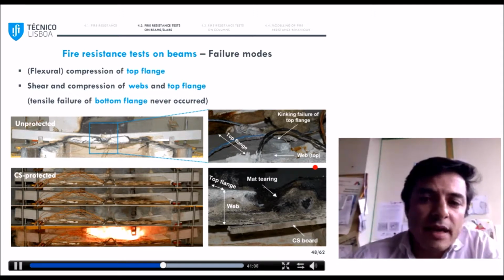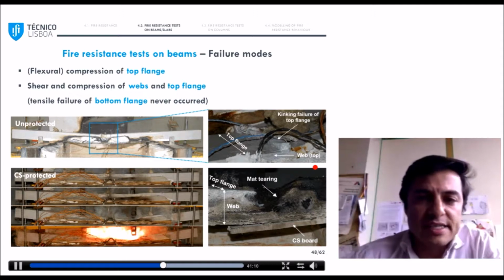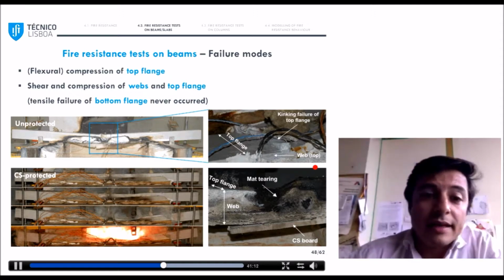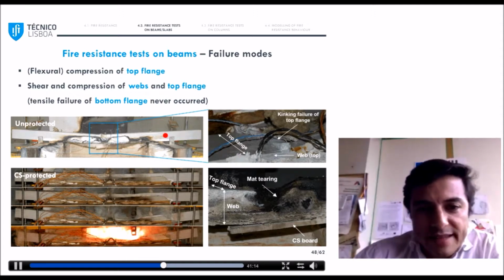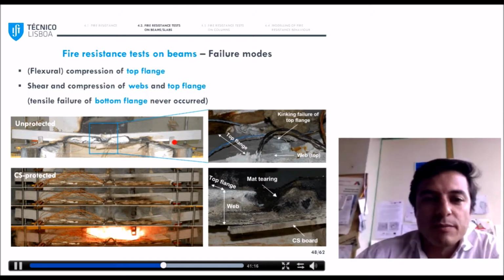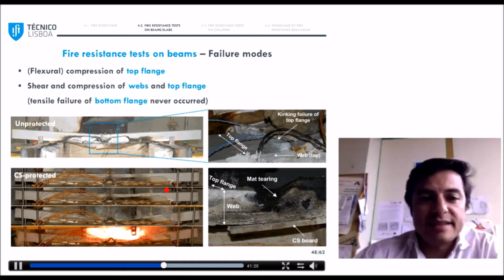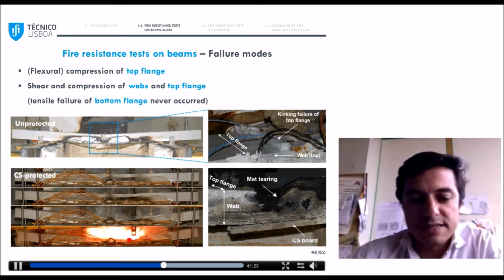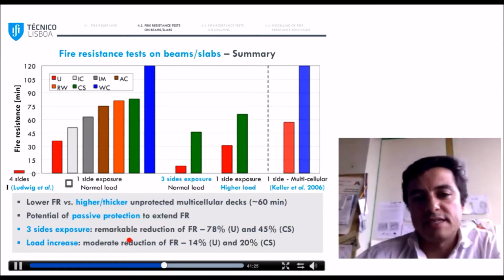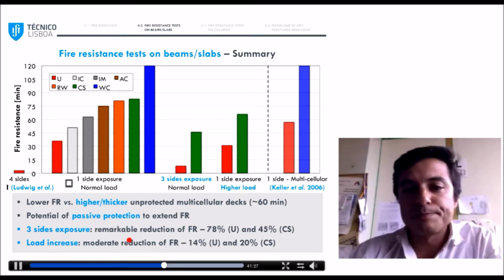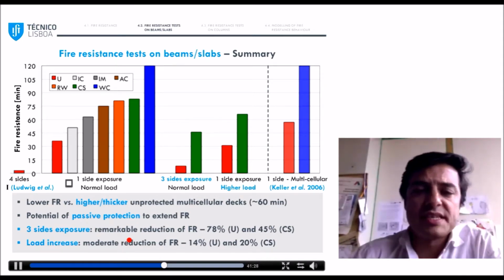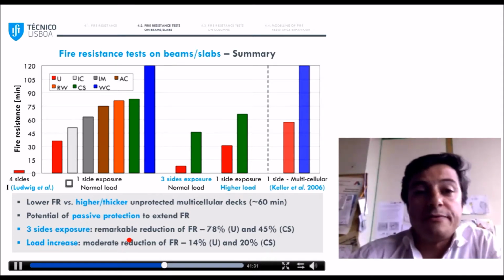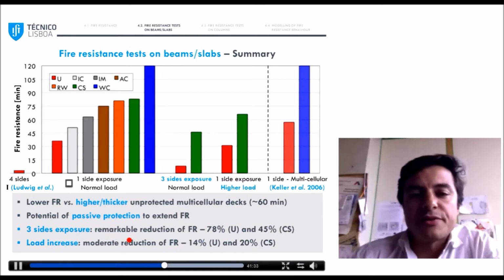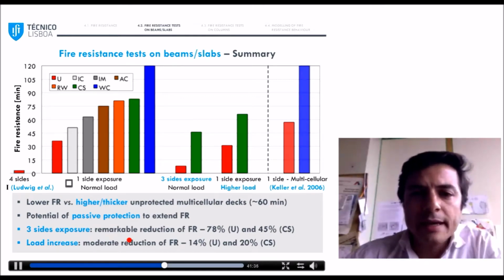And of course this is explained by the much higher residual tensile strength, and also by the fact that the anchorages of the bottom part of the fibers were kept at ambient temperature, and of course this helped in these failure modes. Now, just a summary of the fire resistance of the different elements in bending.